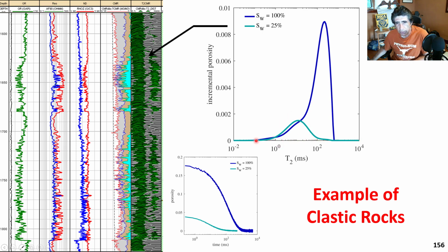And then of course you take the area under the curve and you will get a different porosity, but in this case that porosity is smaller because in the air you don't have hydrogen. So the only hydrogen that you have is in the remaining water, and so essentially that porosity will be equal to the pore volume of the fluid that remains trapped in the rock because of capillary and clay-bound forces. And that is what becomes irreducible water saturation.